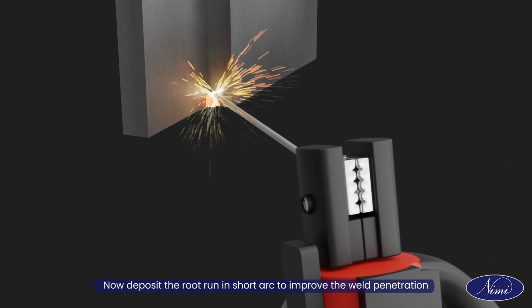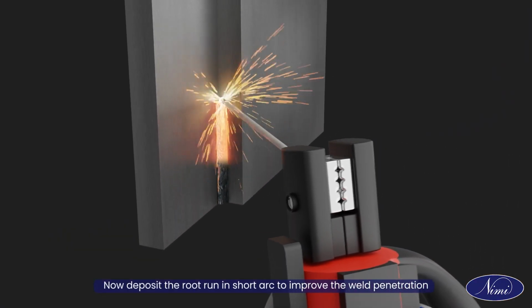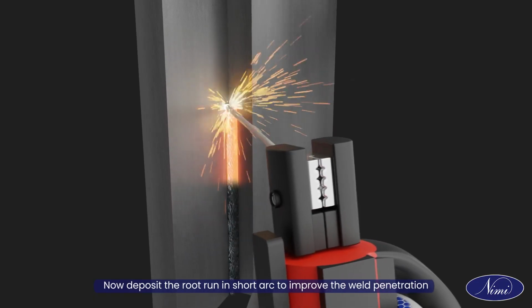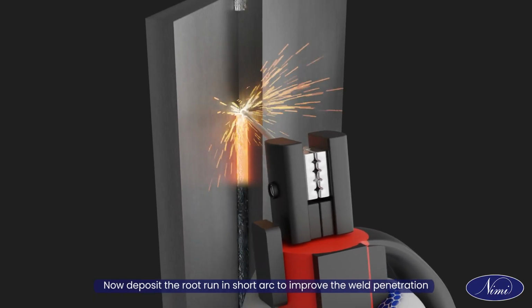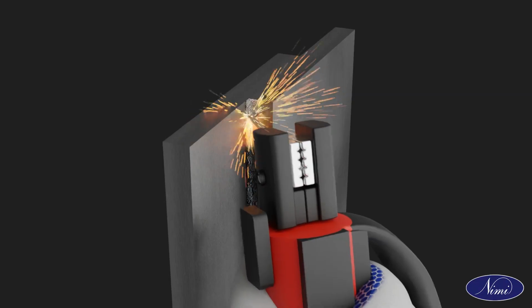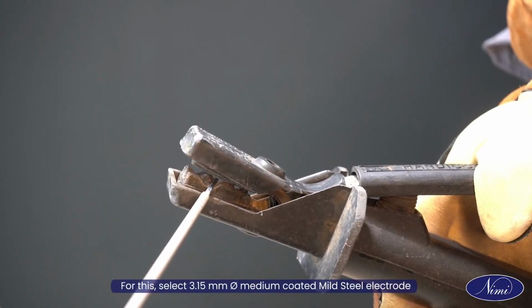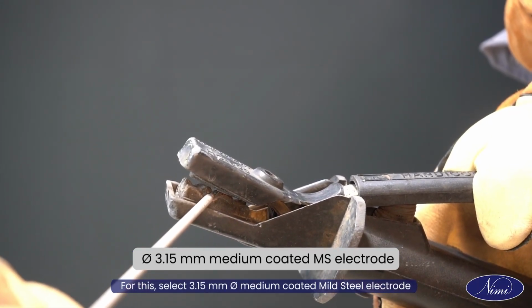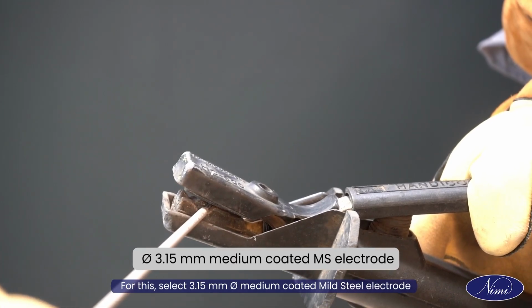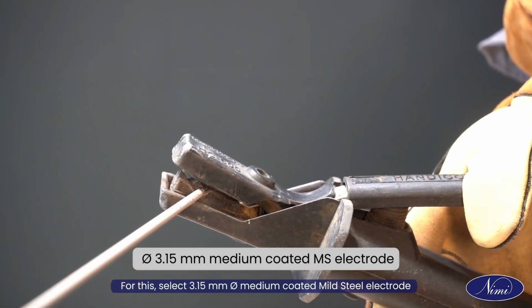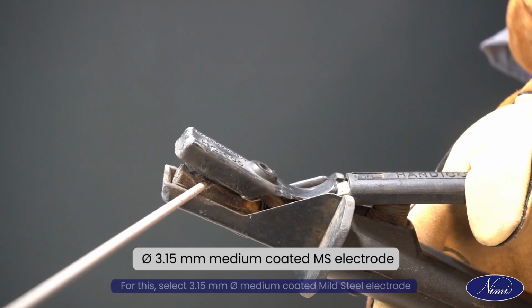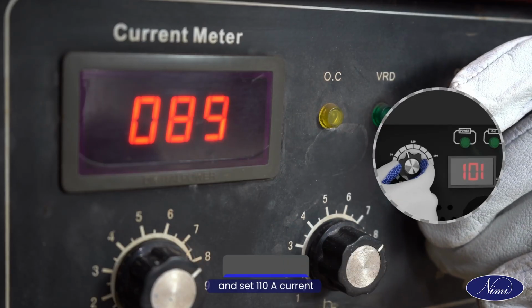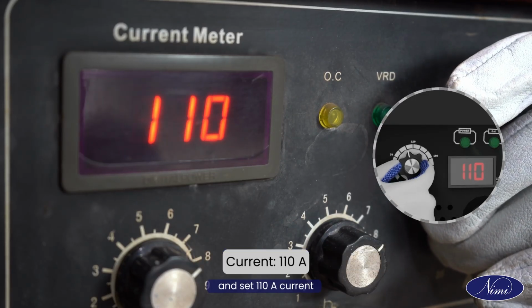Now, deposit the root run in short arc to improve the weld penetration. For this, select 3.15 mm diameter medium coated mild steel electrode and set 110 ampere current.